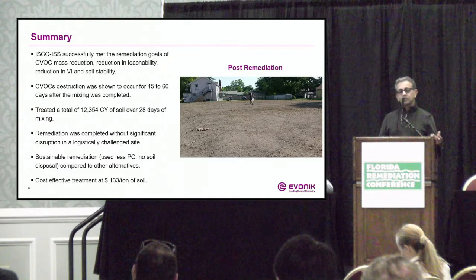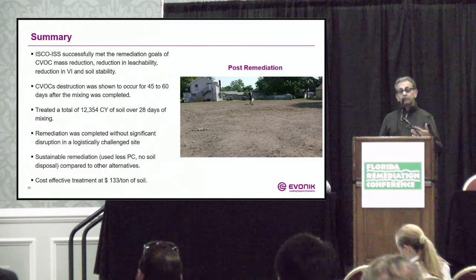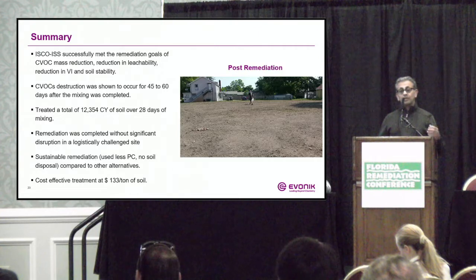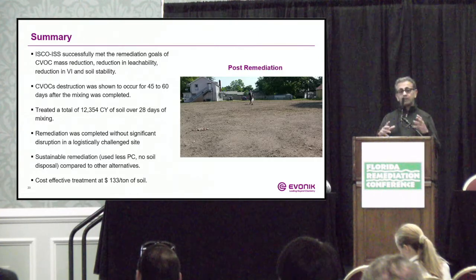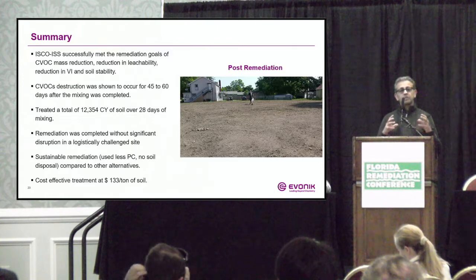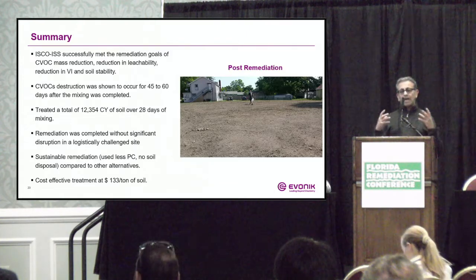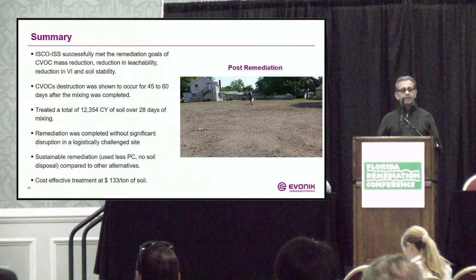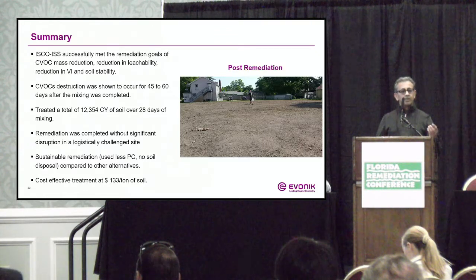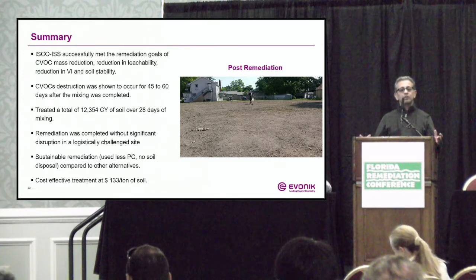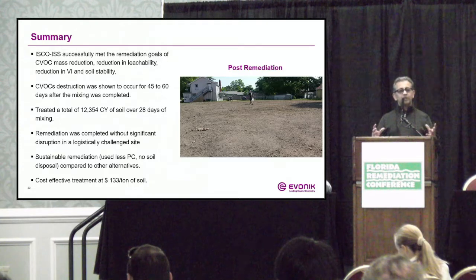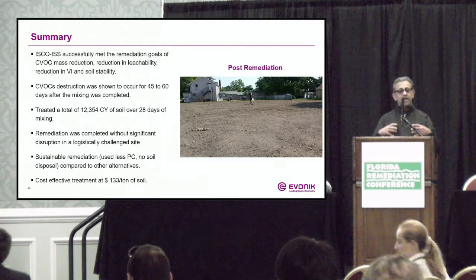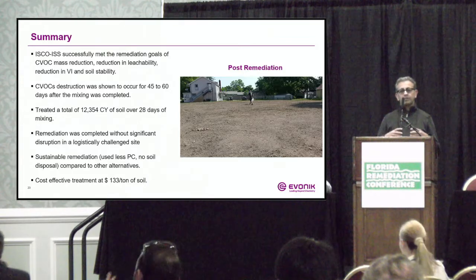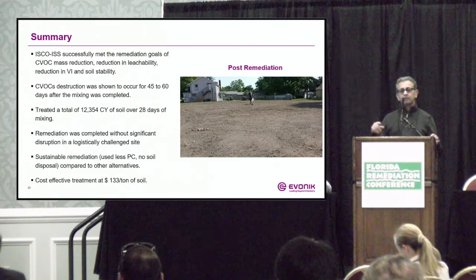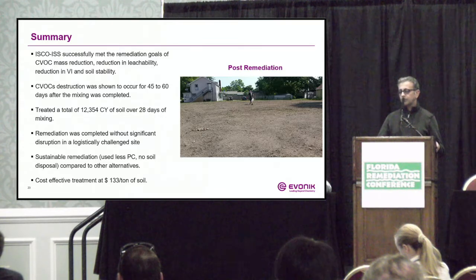The CVOC destruction was observed for 45 to 60 days. So the message there is that the way it was designed, the ISS component was delayed. Usually when ISS is done by itself, within 28 days you want to get your unconfined strength and you want your hydraulic conductivity reduced. But in this particular case, the way we designed it, we had to extend that setting period of ISS so that the oxidation reaction can continue and destroy the contaminants. So that's a key component of combining the two and using the two in a beneficial way.